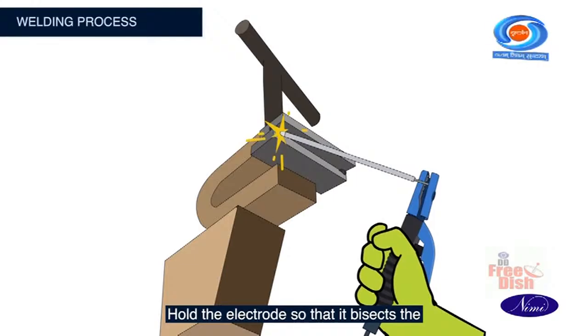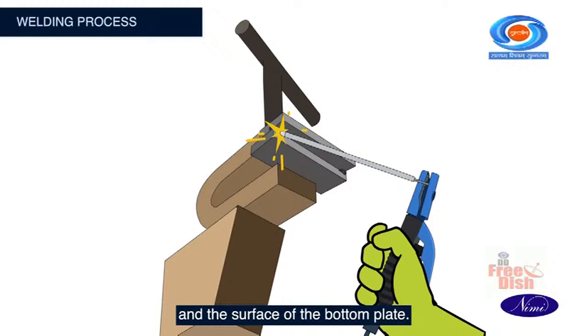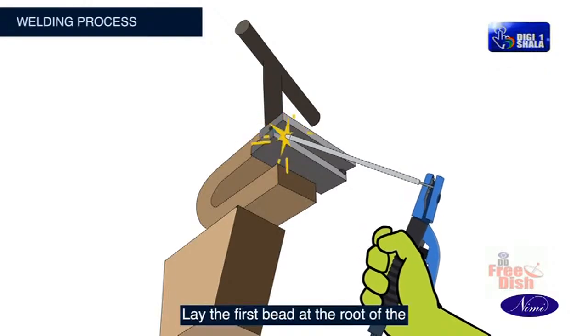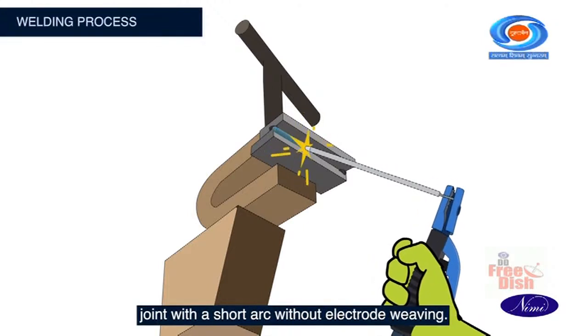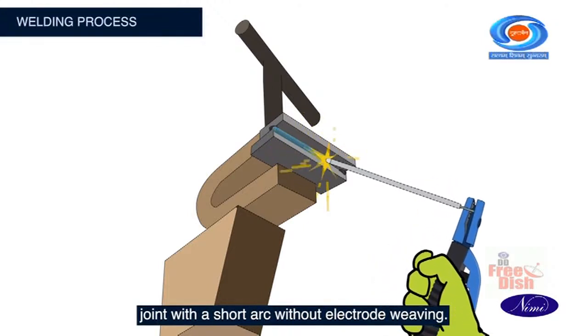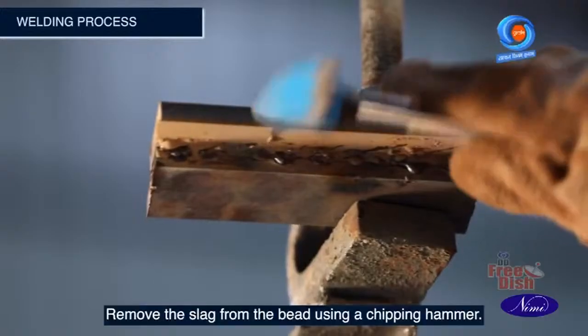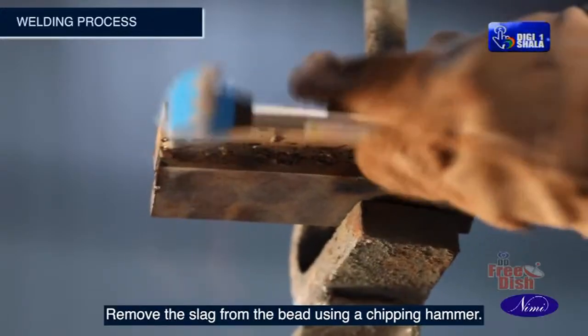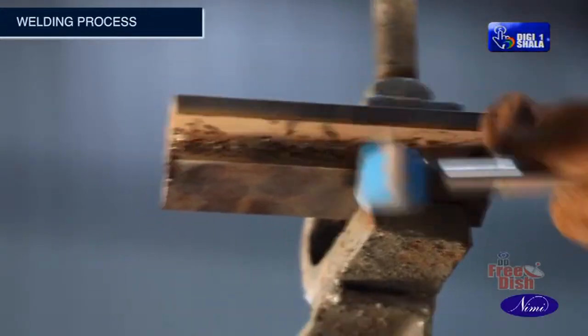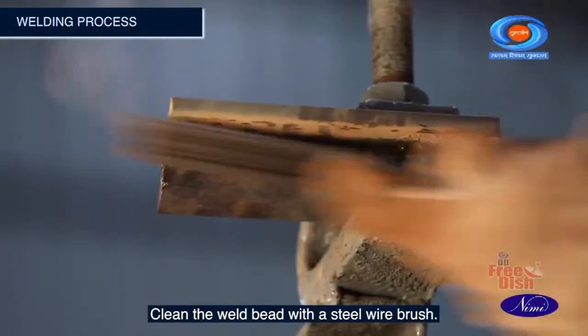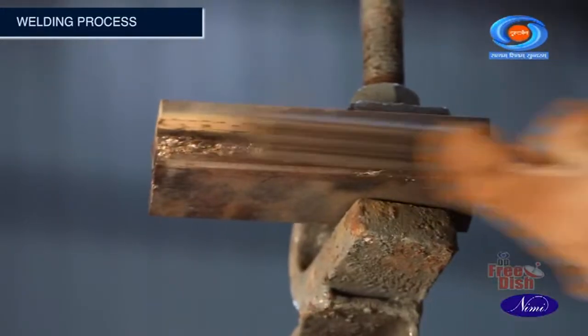Hold the electrode so that it bisects the angle between the edge of the top plate and the surface of the bottom plate. Lay the first bead at the root of the joint with a short arc without electrode weaving. Remove the slag from the bead using a chipping hammer. Clean the weld bead with a steel wire brush.